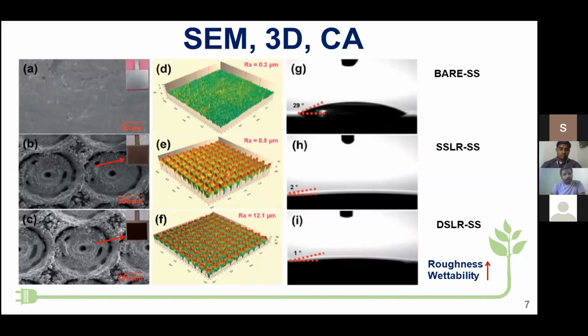Then D, E, F are the respective 3D images of the substrates. When we look at this, the surface roughness is increasing from 0.2 to 12.1. So when we irradiate the metal surface by means of a laser, the surface roughness also increases. Simultaneously, the wettability is also increasing.